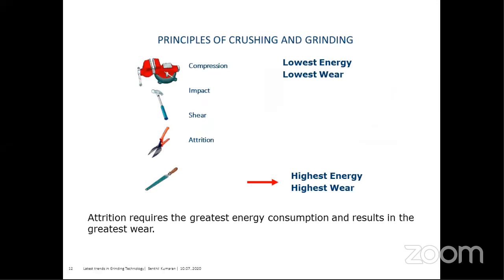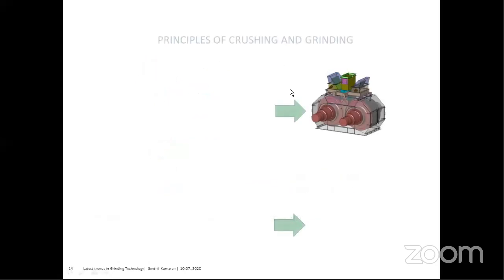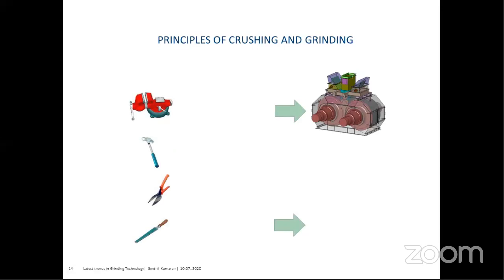Here, compression and impact will have lower energy and lowest wear, whereas in attrition the wear and the energy consumption will be higher, because with impact the fineness cannot be achieved, and with attrition the fines can be achieved.